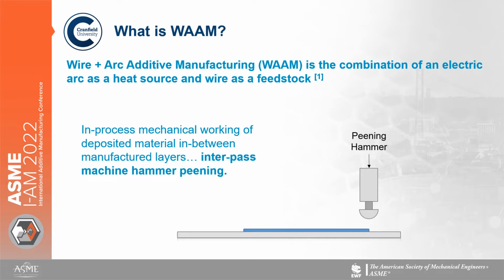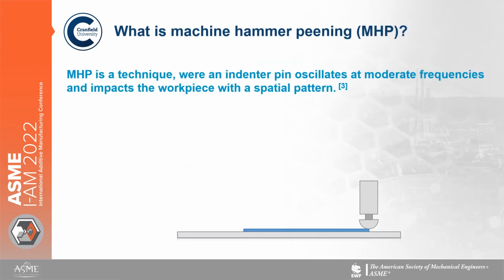we're going to use interpass peening, or machine hammer peening as it's officially known. So what is machine hammer peening? Well, it's a technique where an indenter pin oscillates at a moderate frequency and impacts the workpiece in a spatial pattern. So that's a very complicated way of saying we're going to hammer the deposited material. So as you can see, it's going to oscillate, and as we pass over the deposited layer, we're going to work it, and that we're going to call our peened layer.